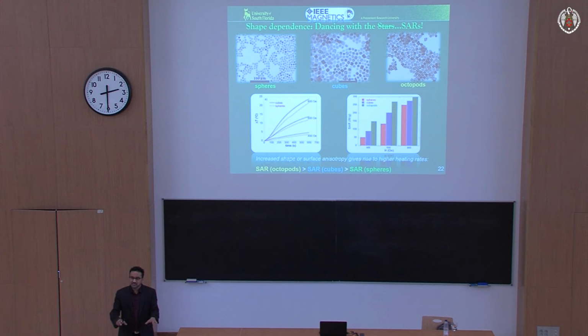Initially it was not embraced well, but now most of the groups understand the effect of anisotropy. That you cannot simply stick with spherical particles, you need to change the aspect ratio. You need to make nanowires, nanorods, and exotic shapes, change the surface anisotropy. So again, very clear that anisotropy has a big influence on this, okay?